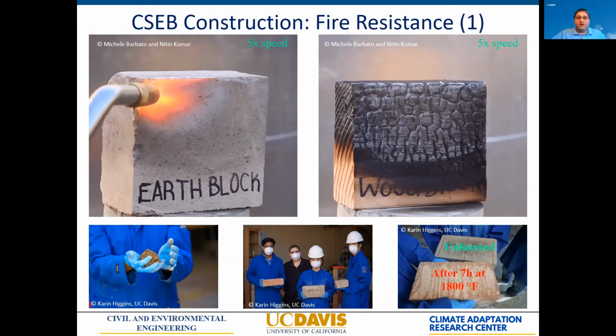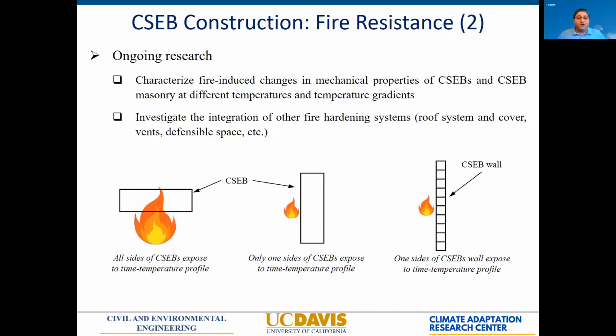We are doing obviously more detailed testing. I don't have all of the results ready yet, so I'm not presenting them. But we are testing the material at different temperatures to see how they respond mechanically at these different temperatures and the effect of fire. Our preliminary results show that up to a certain point, the mechanical properties of the material are improving, because what you're getting is fundamentally fired bricks. So they are even stronger than the originally unburned bricks.